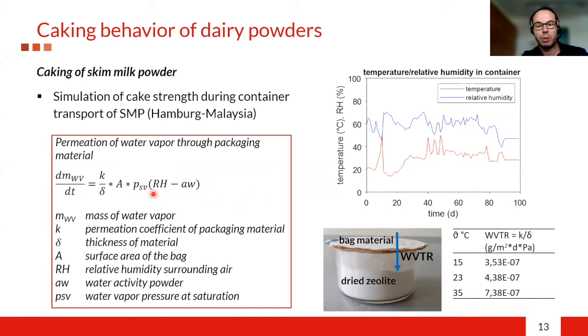Because we want to know the water vapor transfer rate of the packaging material, we first had to estimate this. For this, we placed dried zeolite in a cylinder, sealed it with the bag material, and put it into a climate chamber. We recorded the weight for 3 to 6 months at 3 different temperatures to establish the temperature dependency. So we were able to calculate the permeability of this bag material with the Arrhenius relationship for every temperature.